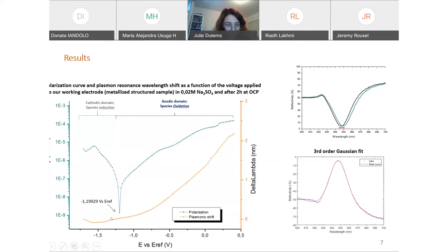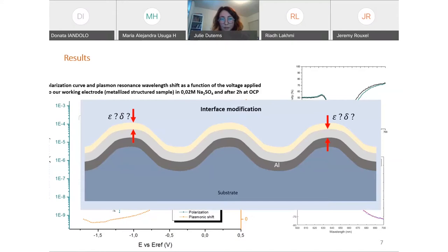If you see it with just this little variation, and starting at this point, we are in the anodic domain, which means there is species oxidation with a higher potential applied. And so during this part, a new passive film has been forced to grow thanks to electrochemistry. The thing is, right now we don't really know the specificity of the passive film. We don't really know what happened during this interface modification. We don't know, for example, the thickness of the hydroxide, or if it's just a pure oxide that has appeared.